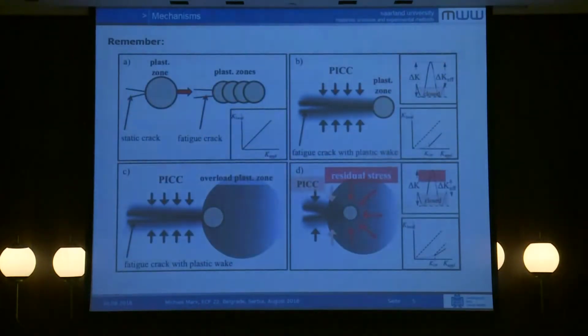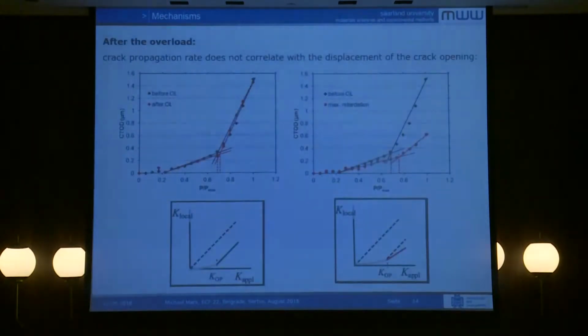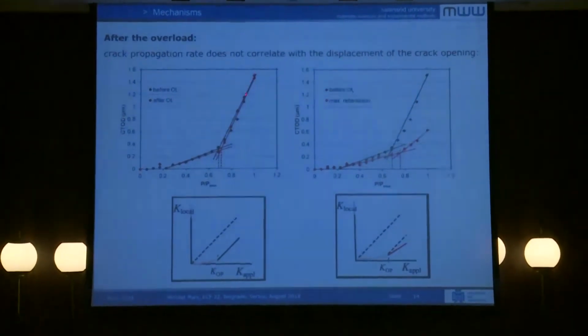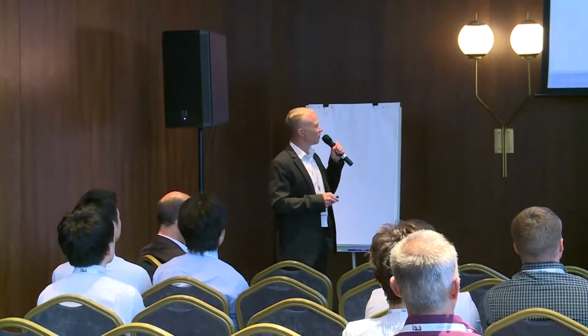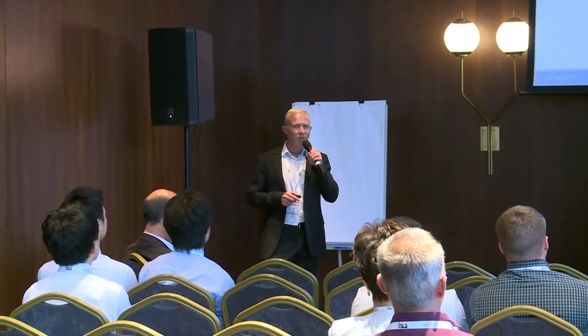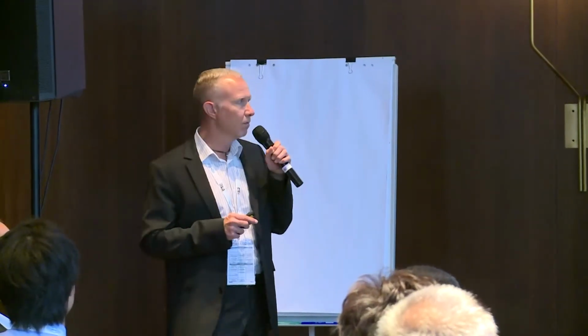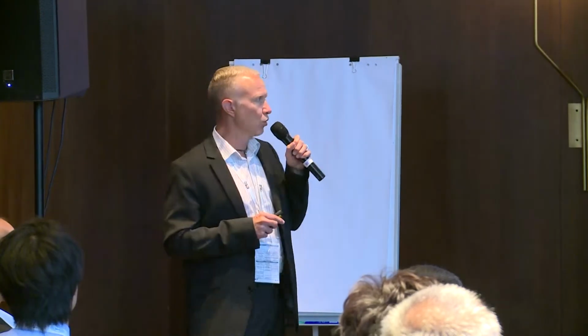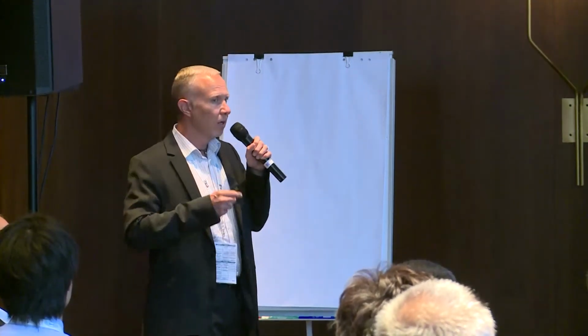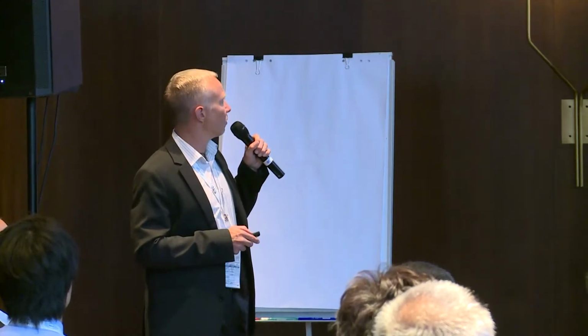Now, what are the mechanisms? Remember again this transparency where you have here your applied K and the local working K, and now we have investigated this to see if we have plasticity-induced crack closure after the overload or if it is the residual stresses. And therefore we measured now the crack tip opening displacement, and this here is before the overload in black, and immediately after the overload you see nearly no influence. So at the beginning, after the overload, there's sometimes even an acceleration of the crack propagation rate, but it's only for a very short time, and then it decelerates up to the minimum crack propagation rate.